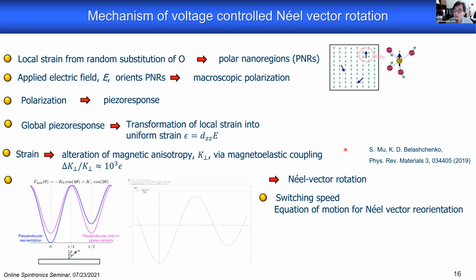Okay, my last comment is about switching speed, which is of course also important, but not yet experimentally studied by us. But we have a collaboration here with theory, with Chalou, and she, based on an LLG-type approach, comes up with an equation of motion motivated by a spin torque driven reorientation of the order parameter, but she can use the same formalism, which can be translated into the formalism of an inverted gravitational pendulum.